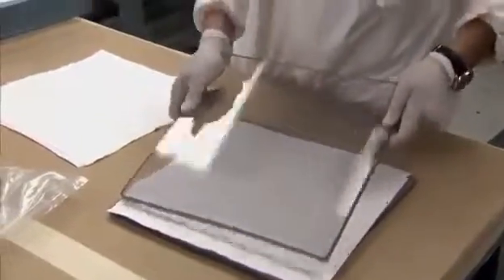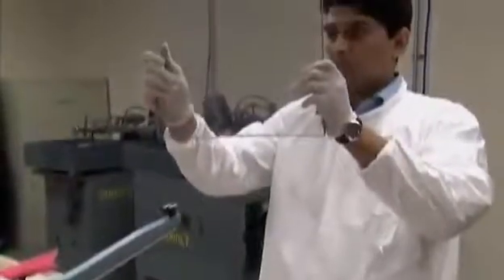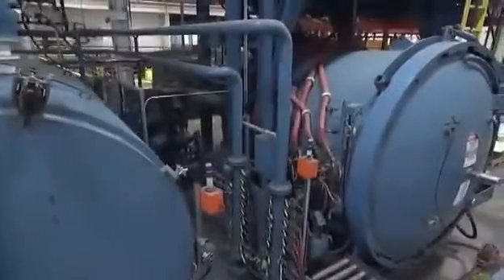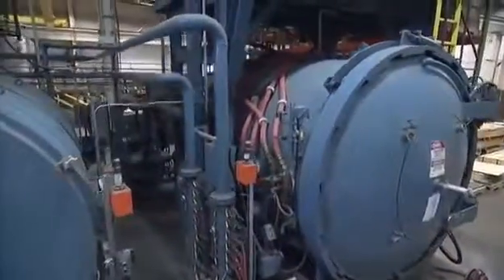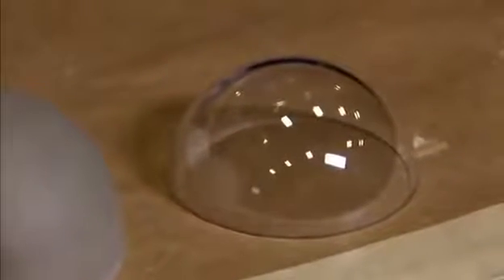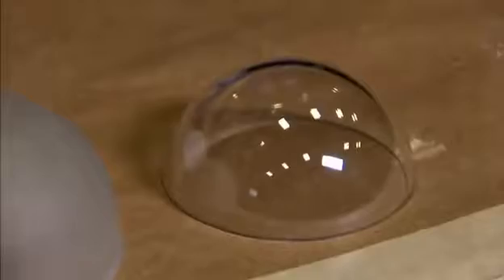And here's what's so surprising. Alon panels are made like ceramic pottery, with the powder pressed into molds and fired in a special kind of kiln. It's very hot indeed. And we are talking well over 1,000 degrees, approaching 2,000 degrees. This is where a miraculous transformation occurs. The aluminum, oxygen, and nitrogen atoms fuse together into a ceramic with 100% density.